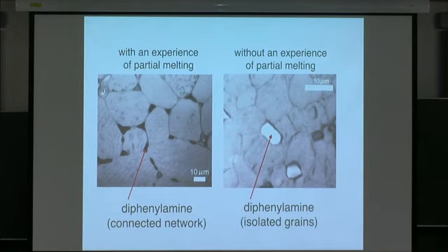Yeah, at least in this experiment, it occurred just below the solidus temperature of the binary system. Of course, I think this material has many other impurities, but the behavior of peak dissipation had a good correlation with the solidus temperature predicted from the borneol and diphenylamine binary system.